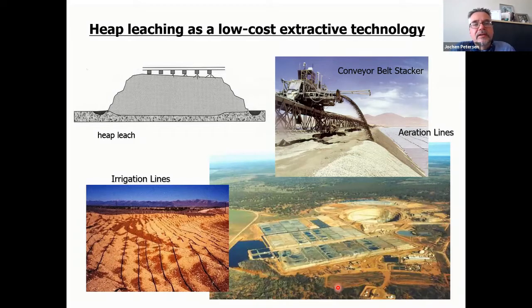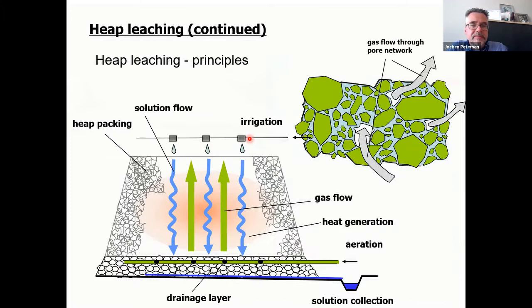But it is a low-cost extractive technology, because, as I showed you in the first slide, it really just consists of piling the rocks on a big pile. You sprinkle solution on it. You put it on an impermeable layer at the bottom, and you extract from the solution that runs through. You extract the metal going further. And then when the heap is exhausted, you can either leave it in place because you've got a perfect drainage collection system already in place, or you remine it, reclaim it, and put it back onto a better disposal site. Both options exist in practice.